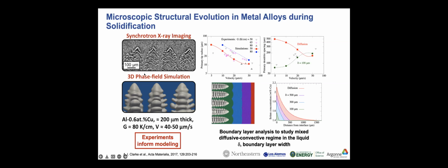We can also do complementary 3D phase field modeling. So these are simulations that were done by our colleagues at Northeastern University of the different experimental conditions that we probed. And similarly, we can pull out quantitative information as well and do this head-to-head comparison. So here we're looking at primary tip radius versus velocity. And here all the open symbols correspond to experiments, and the red and the blue correspond to simulations. So we do pretty well with respect to that.